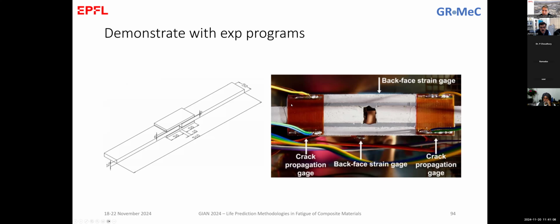And when we talk about joints, we don't talk anymore about purely life of the joint, but we want to see also how the damage progresses. And damage in a joint is usually a crack that is initiated either artificially or physically, and without any pre-crack in several locations. It might start here, it might start there, wherever. And we need to follow this crack propagation.